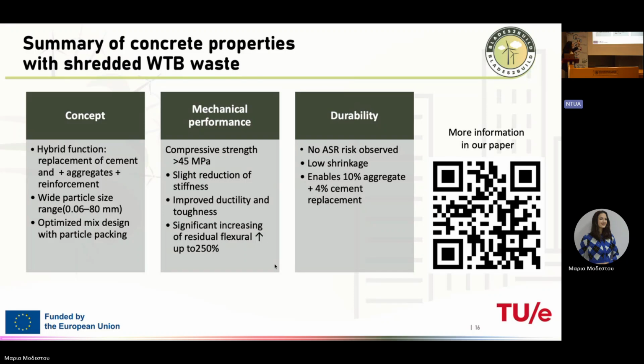We used a wide particle range of this waste. It's from 0.06 to 80 millimeters basically, but the core of this waste is up to 20 millimeters that we use. And we use optimized mix design. So under these terms, we can get compressive strengths up to 45 MPa, slight reduction in stiffness, improved ductility and toughness, and increasing residual flexural strengths. No alkali silica reaction risk observed, low shrinkage, and we can replace 10% of aggregate, around 4% of cement.